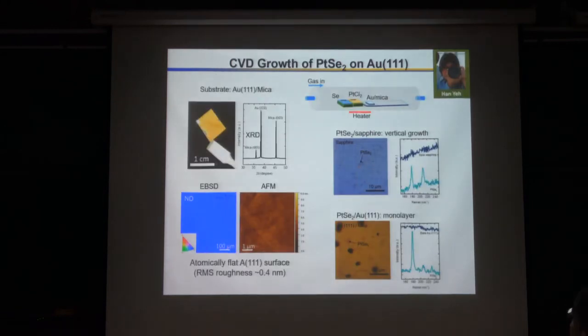The third example is we grow PtSe2, also on gold 111. So the story is the same, so I don't need to repeat. Actually, PtSe2 is not easy to nucleate on such a sapphire crystal, so it usually shows some island growth. But on gold, it will form larger flakes with only monolayers here.